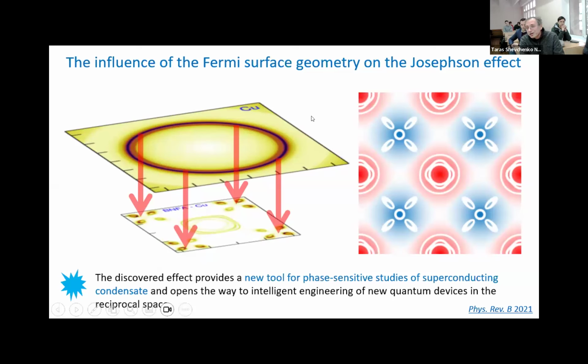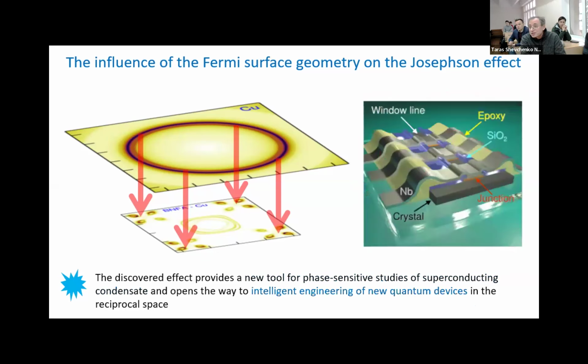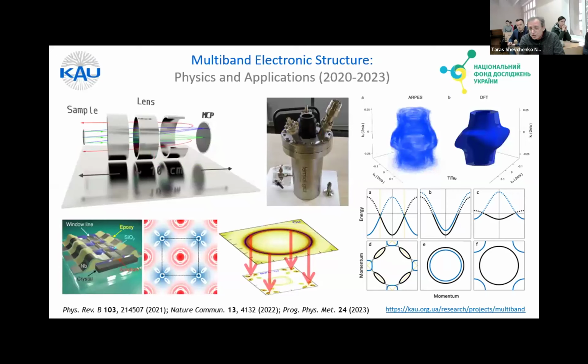because if we consider just tunneling of superconducting pairs, they jump from one material, which is niobium, which is quite homogeneous, let's say, and they jump to the Fermi surface of the iron-based superconductors. And here I show the Fermi surface in white, and red and blue are the signs of the superconducting order parameter. Therefore, if electrons jump here and here, you have this destructive interference. But if you have such a filter, then electrons predominantly jump to the part of the Fermi surface where the superconducting order parameter is of one sign, and therefore this parameter is increased, and the frequency will also be increased.